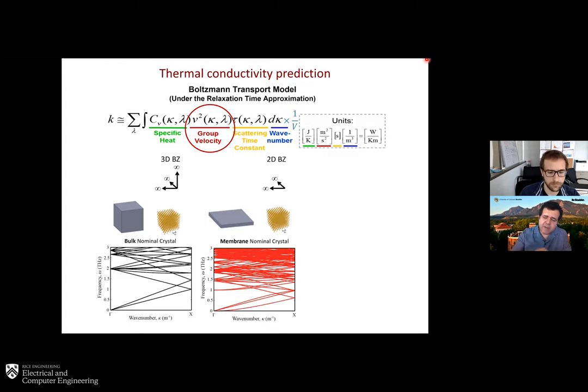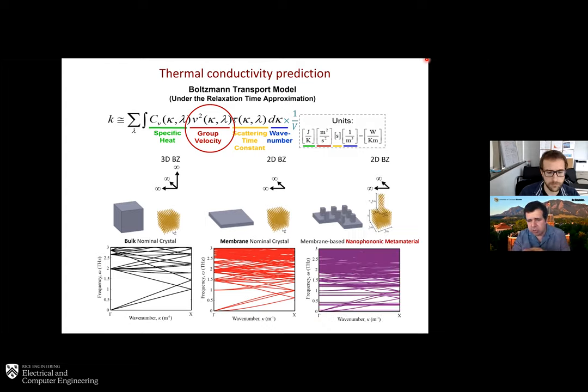So this is, in fact, where the MPM concept comes into play. Just like I was showing you before in the form of schematics, now we actually have a model shown there on the right, which is an atomic scale model of a membrane with a pillar. In the phonon band structure shown there, you can see part of it resembles that of a plate, because the MPM is, in fact, a membrane or a plate. Except that now we have these pillars, and what these pillars do, as I said earlier, is form these vibrons. These are nothing but resonances.